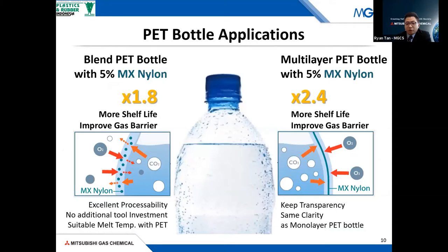In the PET bottle application, by using MX nylon in the same preform weight as the original PET preform, we are able to achieve an improvement of barrier properties by about 1.8 times for the blend, or 2.4 times for the multi-layer. This extension is due to an increase in barrier properties, and we will show you some data, some examples later.